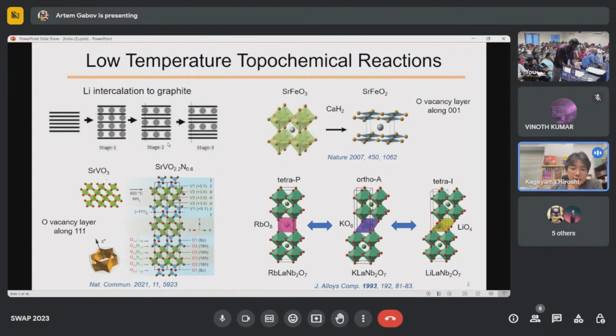Another example shown on your top left is the topochemical reaction using the iron oxide with perovskite structure. By using calcium hydride, you can eliminate the so-called apical oxygen to produce strontium iron oxide bearing square planar iron coordination, which is very rare. But in this particular case, the oxygen vacancy is created along the 001 direction. But our recent finding, topochemical reactions shown on your bottom left, is another example where the oxygen vacancy layer is created along the 111 direction of the perovskite structures.